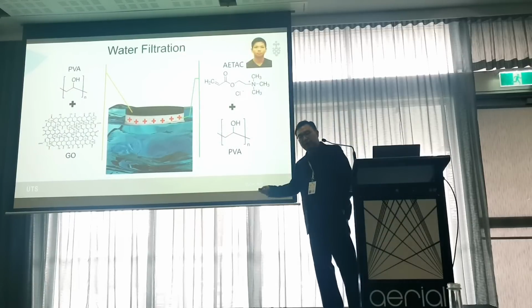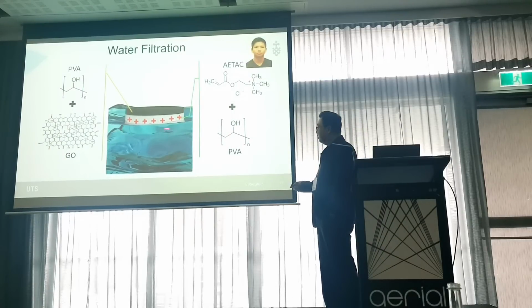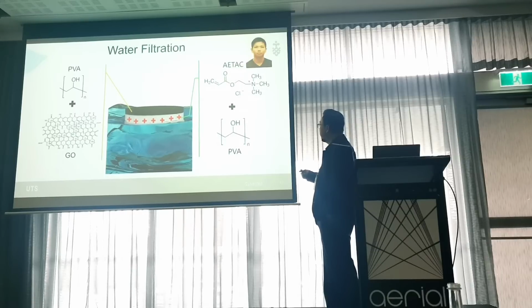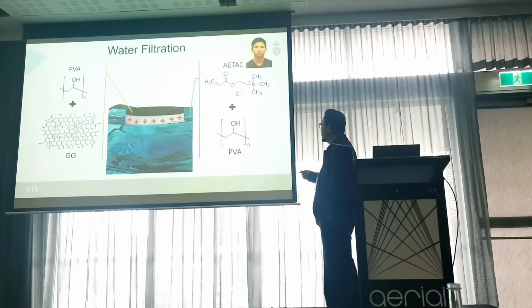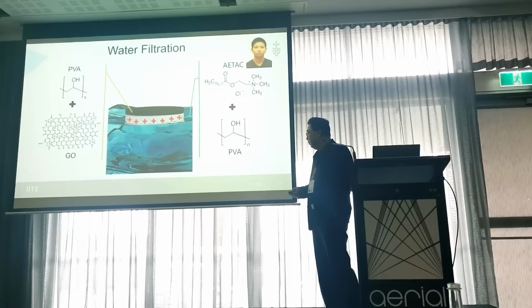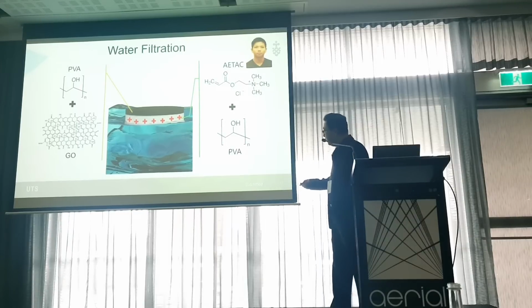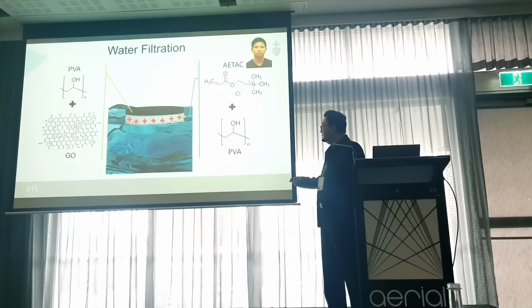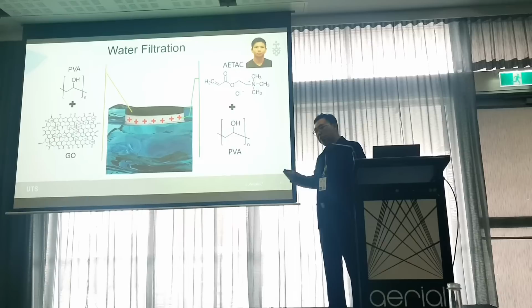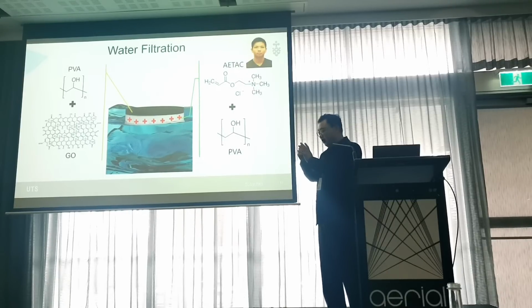Like our last study, we developed a novel dual-layer hydrogel system. The top layer is composed of PVA and graphene oxide, and the bottom layer is made from a polymer containing a positively charged ammonium group. We also added a certain amount of PVA because PVA can enhance the compatibility between these two layers. Different hydrogels have different swelling ratios, and we don't want these two layers to break apart.